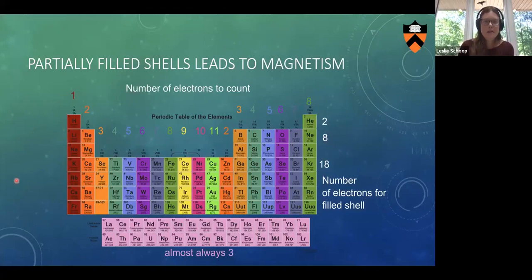That doesn't mean that there aren't a lot of papers which claim something like calcium nitride 1-1 would be magnetic. And think about it: if you put calcium, which is 2 electrons, and nitrogen, which is 5 electrons, you would get 7. So you have an open shell system. If you plug this into a DFT code, you would get something magnetic. It doesn't mean that this phase exists or is stable. So I'm just putting out a warning sign: if you live only in the main group elements, it's very unlikely you have an open shell system.